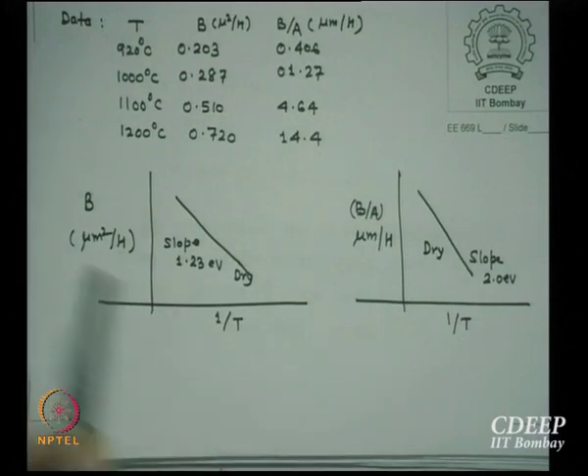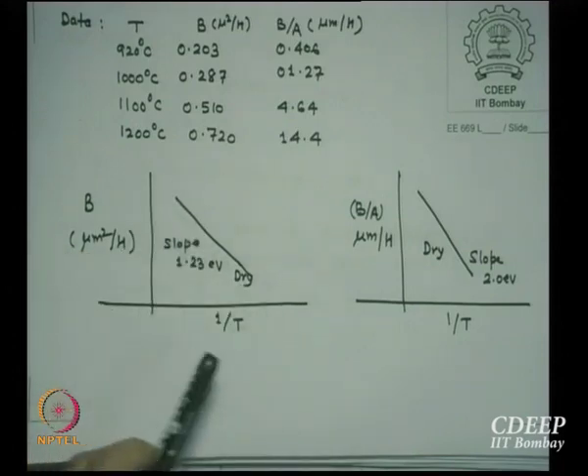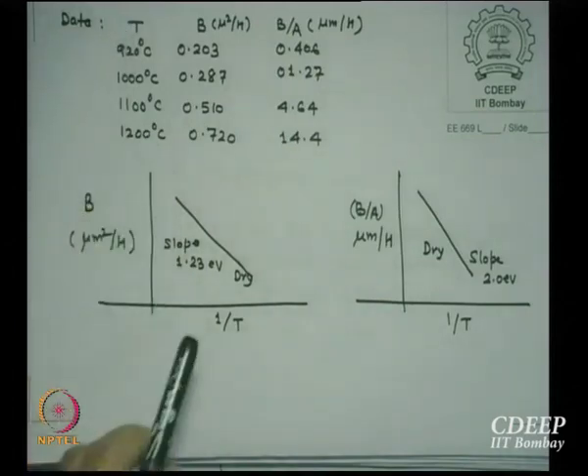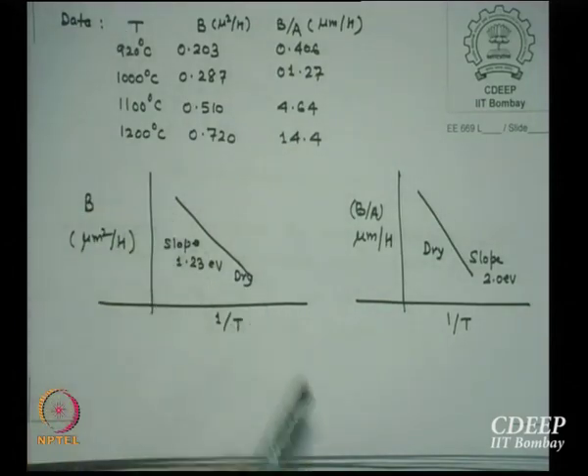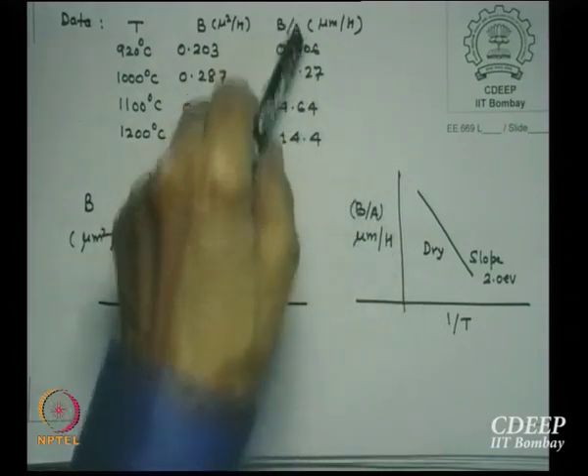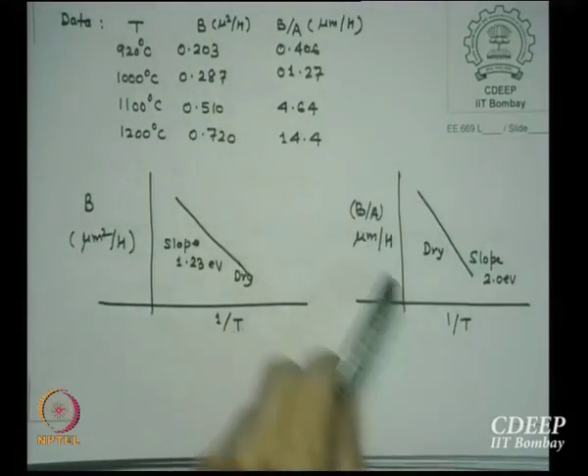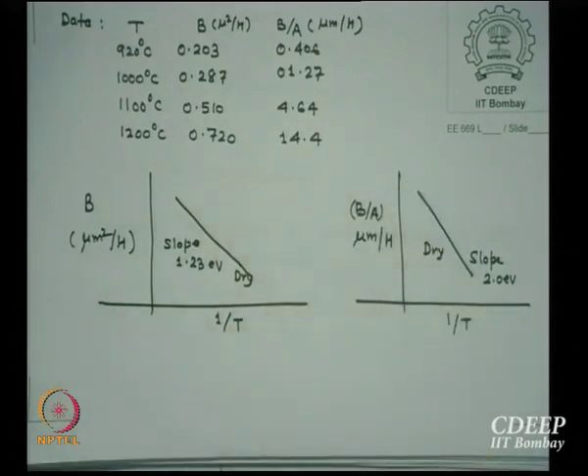So if I plot now B versus 1 upon T for dry oxidation, of course I have not talked about this, but we will come, dry means only pure oxygen is passed. If I have a dry oxide and I plot B versus 1 upon T, I see a straight line, and its slope is 1.23 electron volt. If I repeat the same graph for B by A versus 1 upon T, I get a slope of 2 electron volt.